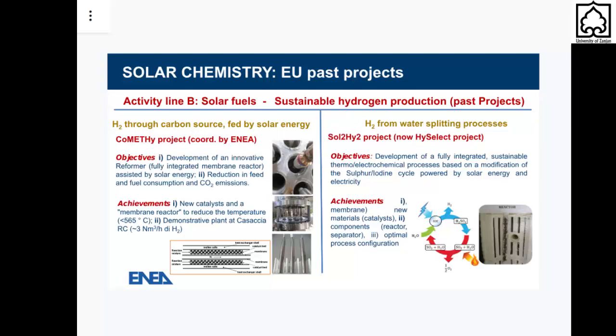And so they were referring to the two approaches that I've just mentioned in the previous slide. To the first approach belongs the CoMETHy project, which is coordinated by ENEA, which was aimed at developing a compact and innovative reforming reactor to convert carbon fuels, for example, methane and biogas, into pure hydrogen through steam reforming, but at low temperature, let's say about 450, 550 degrees C, assisted by solar energy.